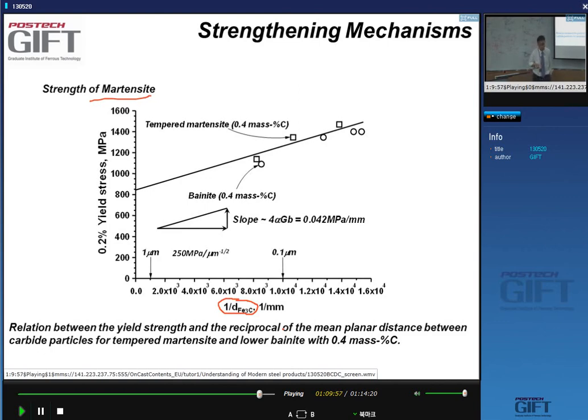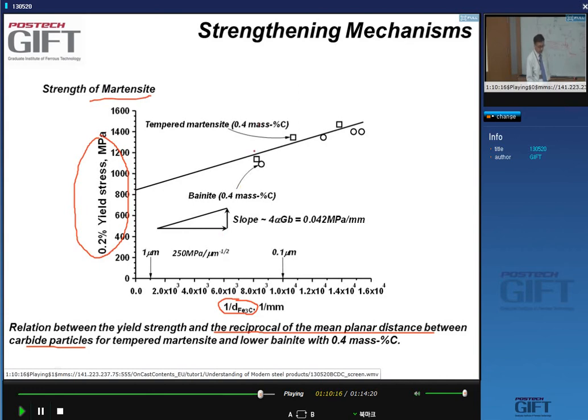And here you see the relation between the yield strength of martensite and the reciprocal of the mean planar distance between carbide particles in tempered martensite. You know that when you go from martensite to tempered martensite, you take the carbon out of solution and replace it with carbide particles in the lattice, right? And you see the same thing as what we just showed for these niobium carbide precipitates. If you look at the distance between the particles, and you do 1 over the distance, so that means more carbide particles going this way, you get a strengthening effect due to high volume fraction of carbide particles.